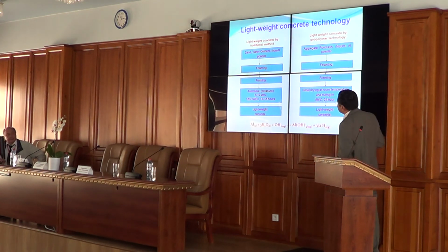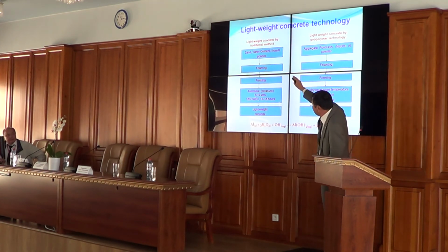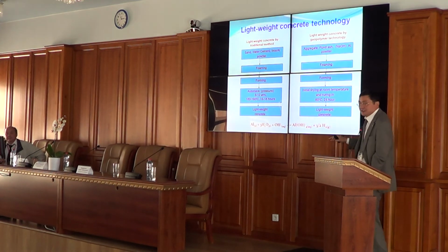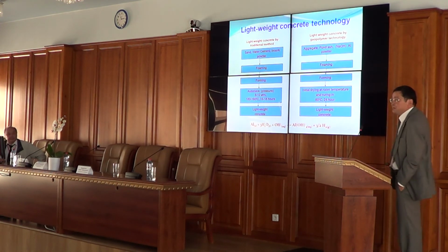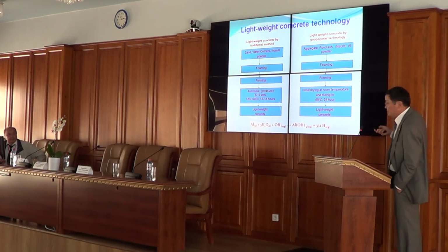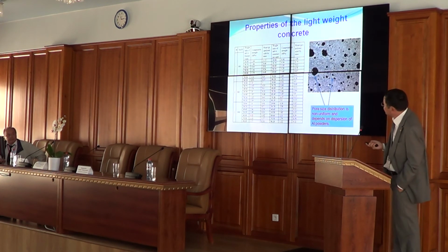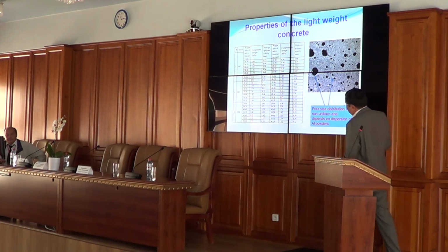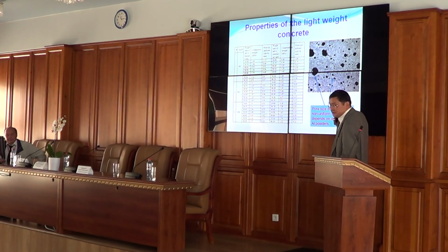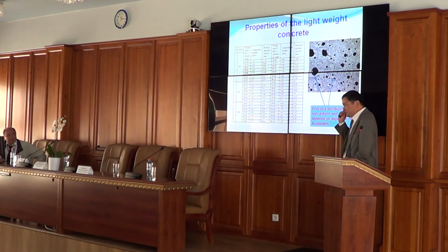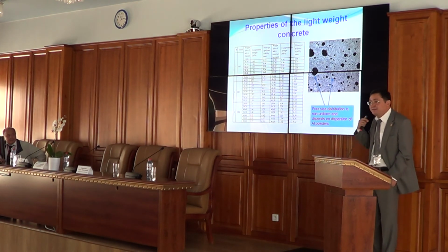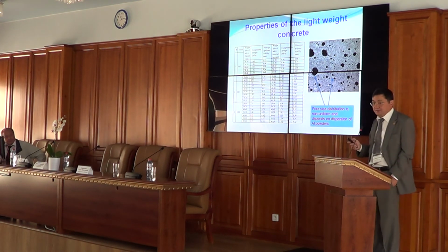In lightweight concrete technology, there is the lightweight concrete traditionally made this way, and then the lightweight concrete produced by our new method, where we get quite a good compressive strength value, probably 3.1 megapascals, which is 2 times higher than that allowed by the standard. This is a good value. One problem is that the pore size distribution is non-uniform, which is difficult to control.